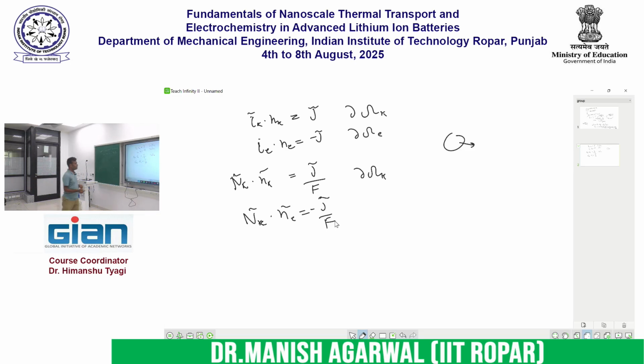Apart from that, you have the boundary conditions. I will not touch too much upon them, but the only thing I will say is that at these boundaries, at the top and at the bottom, the current flowing out is 0, and the mass flux flowing out is also 0. So at this boundary it is I tilde_k dot n_k equal to 0, and N tilde_k dot n_k also equal to 0.